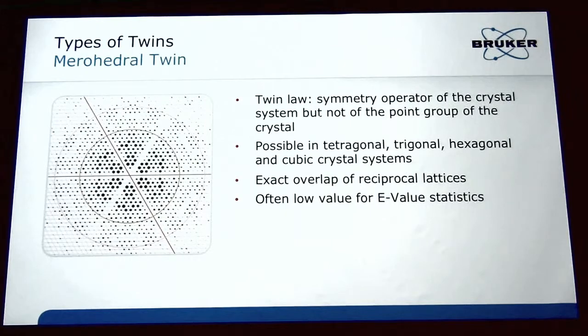So you might have a crystal that indexes and looks like it's P4/mmm, when actually it's P4/m, with a twofold relationship between two different domains. And that relationship we call the twin law. So it's mimicking higher symmetry because there's two different orientations of essentially the unit cell and the crystal. In this case, the two diffraction patterns overlap completely. So just looking at the diffraction pattern, you would think nothing was wrong.